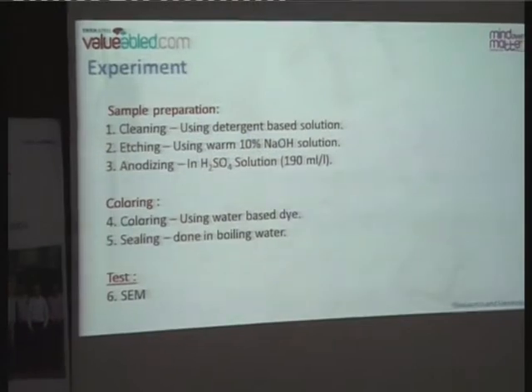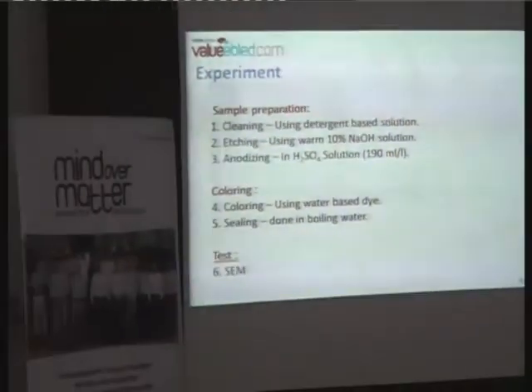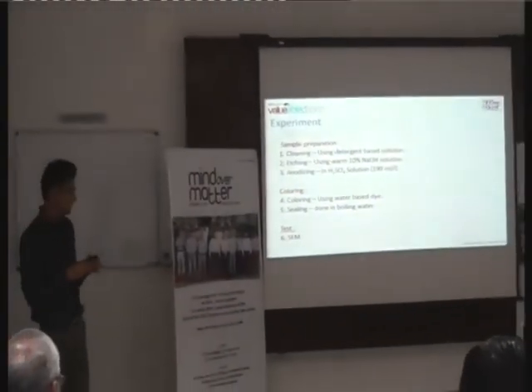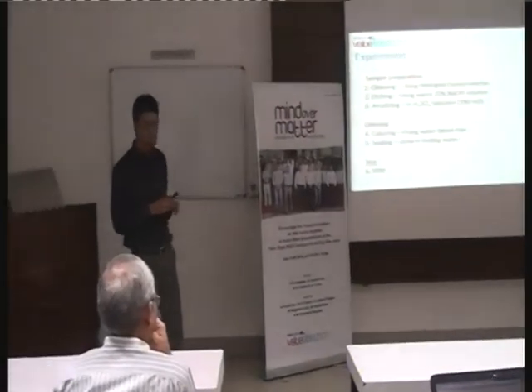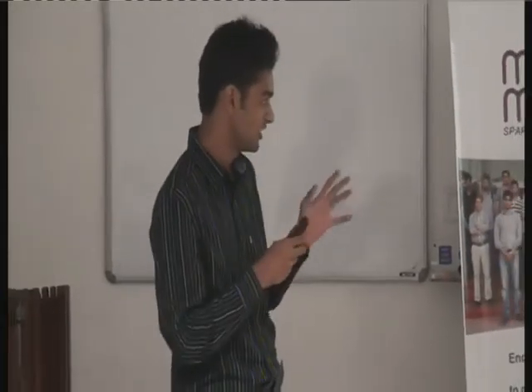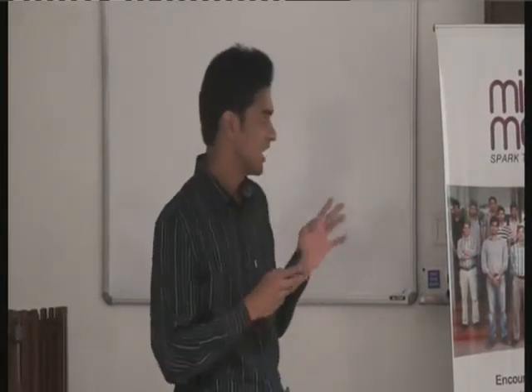After anodizing, for coloring, I used a water-based dye, which is easily available here, and after coloring, the sealing is very important. Otherwise, the corrosion resistance property will decrease. For sealing, I just put the sample in boiling water for 15 to 20 minutes, and in this reaction the aluminium oxide reacts with water and forms boehmite, which is hard and transparent, and it seals the pores.